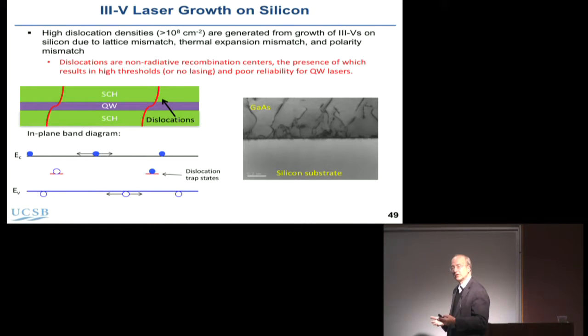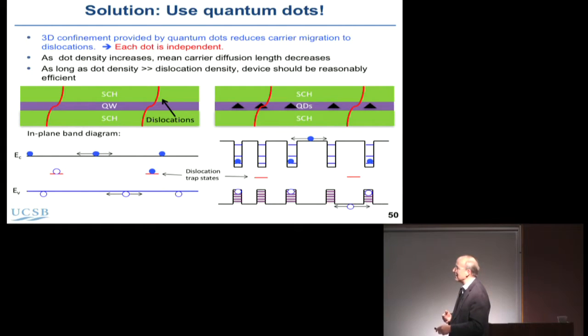So basically the whole material is black. Everything gets recombined at dislocations. But if you can put a high density of quantum dots in there, we put about 500 dots per dislocation, so 5 times 10^10 density, then indeed a few of them have degradation, but only 1 in 500 sees that.